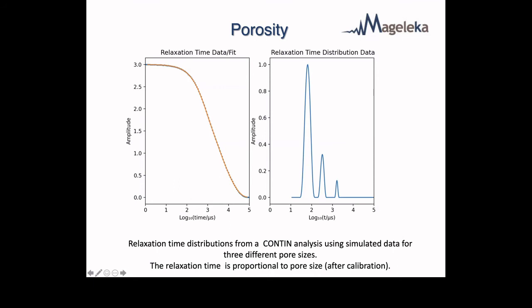So this is synthetic data. It's from 3 different pore sizes. And you can see we get 3 different peaks in the relaxation time distribution. This is still in time, but you can convert this axis directly to size, again, if you know the Ka parameter.